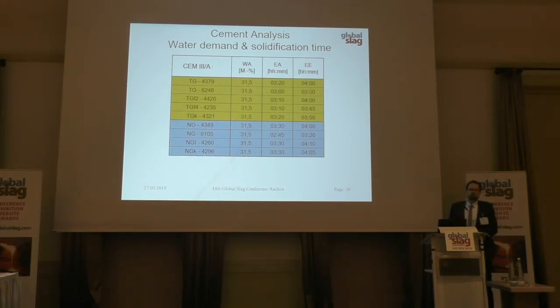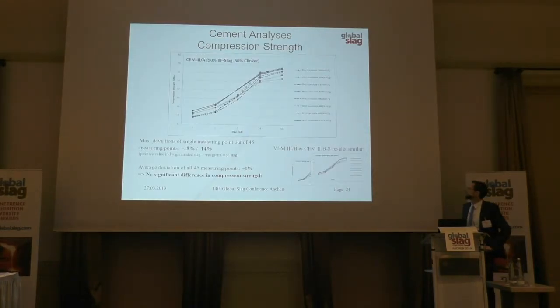We have also done cement tests, so we have done different ratios of clinker and dry granulated product cement mixtures. One of the results is the water content, where there's no remarkable difference, and another result is the solidification time, when it starts and when it ends. There's also really no difference. The most important point, of course, for the cement tests is the compression strength test.